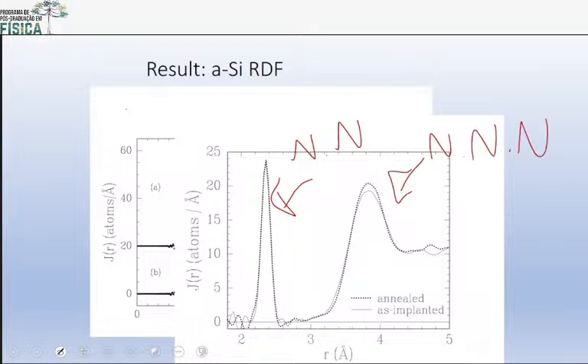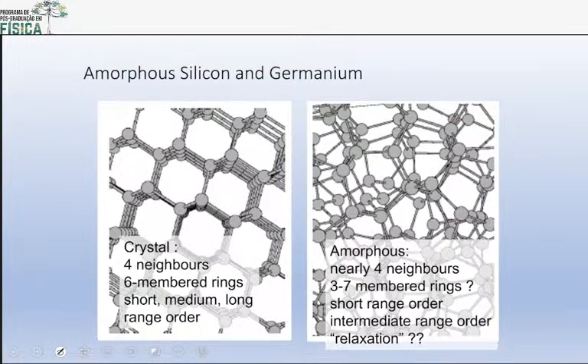Okay, the next nearest neighbor, the second one. And what it tells us is that even though amorphous silicon is like this here on the right, this big mess of, oh yeah, here. So crystalline has 4 neighbors. They call 6-member rings, long range order. While amorphous silicon, which is very important for technology, has very close to 4 neighbors, but maybe not exactly. And people have a hard time being able to describe the structure.